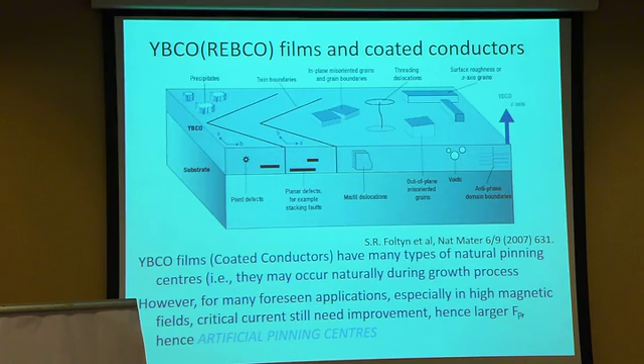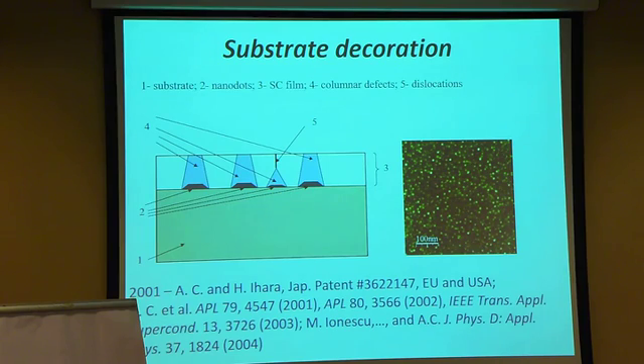There are many types of natural pinning centers in YBCO films and coated conductors, and these are from a very nice review paper by Foltyn in 2007, Nature Materials. So we see here many types of natural pinning centers, which occur naturally during the film growth. However, for many foreseen applications, especially in high magnetic fields, critical current still needs improvement, hence we need a larger pinning force, and hence we need artificial pinning centers.